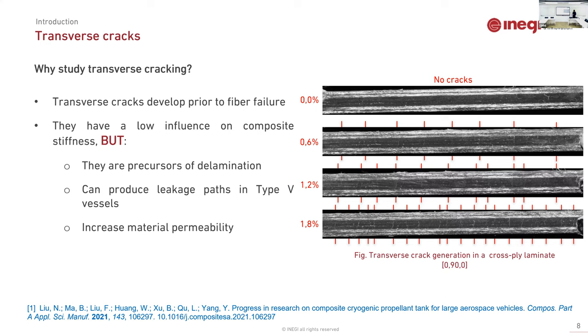Among these kinds of problems, why study transverse cracks? Transverse cracks are a kind of failure that is very common in composite materials and usually happens before the fiber fails. So the composite lamina will not break, it will only have transverse cracks.